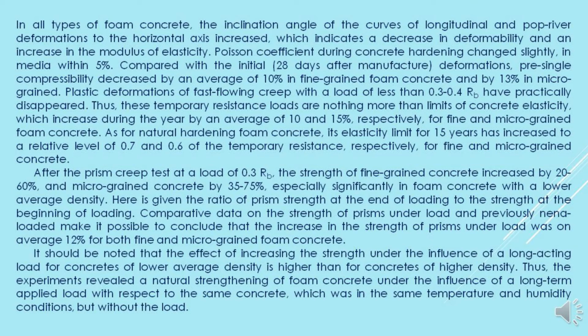After the prism creep test at a load of 0.3 RD, the strength of fine-grained concrete increased by 20 to 60% and micro-grained concrete by 35 to 75%, especially significantly in foam concrete with a lower average density. Here is given the ratio of prism strength at the end of loading to the strength at the beginning of loading. Comparative data on the strength of prisms under load and previously unloaded make it possible to conclude that the increase in the strength of prisms under load was on average 12% for both fine and micro-grained foam concrete. Thus, the experiments revealed a natural strengthening of foam concrete under the influence of a long-term applied load with respect to the same concrete, which was in the same temperature and humidity conditions, but without the load.